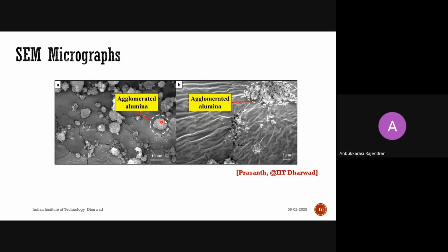This is another sample where alumina is embedded in an aluminum matrix. To reveal how the alumina is distributed in the matrix, we prepare the sample and try to understand the distribution of particles under SEM. In some places it is not mixed properly, and there is agglomeration. So this information also we can get from SEM. It may not require the etching process, but as I mentioned, the polishing is a must.